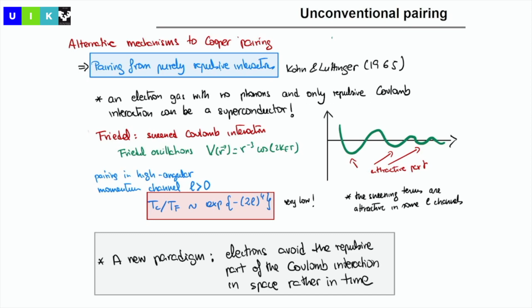So we just saw this harmonic expansion in the orbital degrees of freedom. So we expect that the pairing is going to be in a high momentum channel. Now if you introduce this mechanism into these equations that we had in the BCS, and this was a question also yesterday, in principle we could put another mechanism that is not electron-phonon because the equations are still valid. If we put this type of mechanism, then the predicted critical temperatures are extremely low. You see it's a power of L, exponential minus L to the 4. This was a little bit disappointing, that such a mechanism would give you very, very, very low TCs.